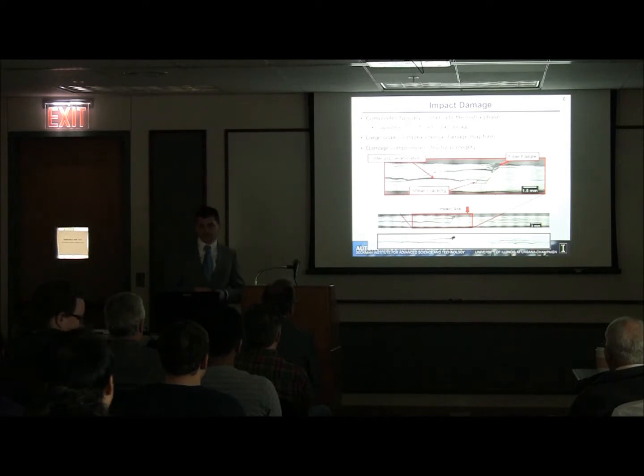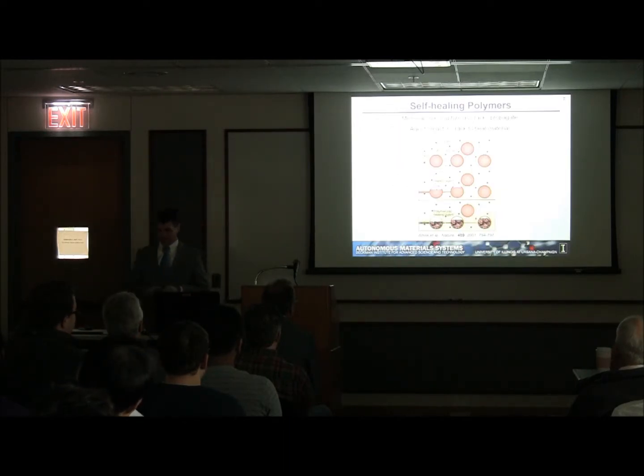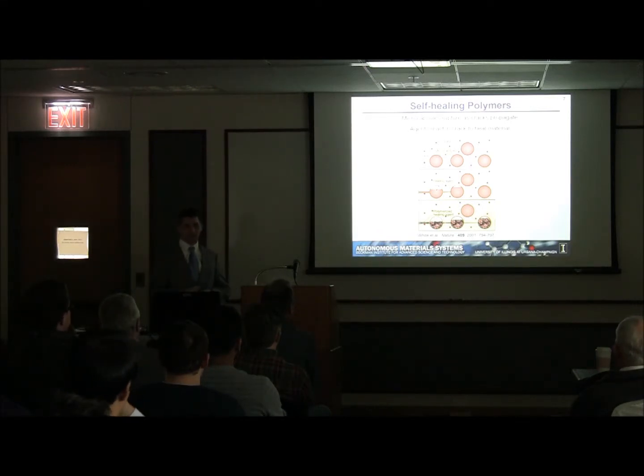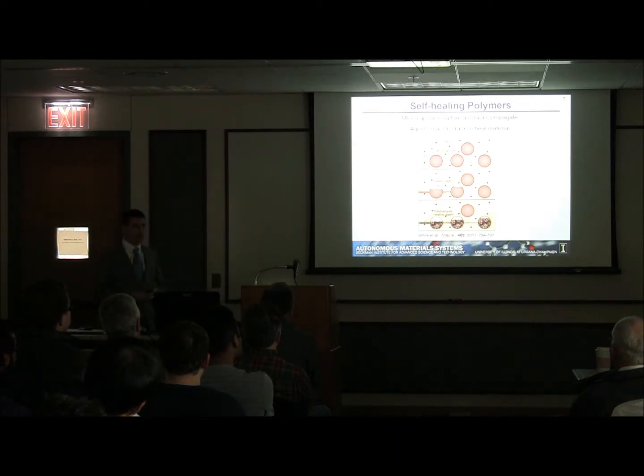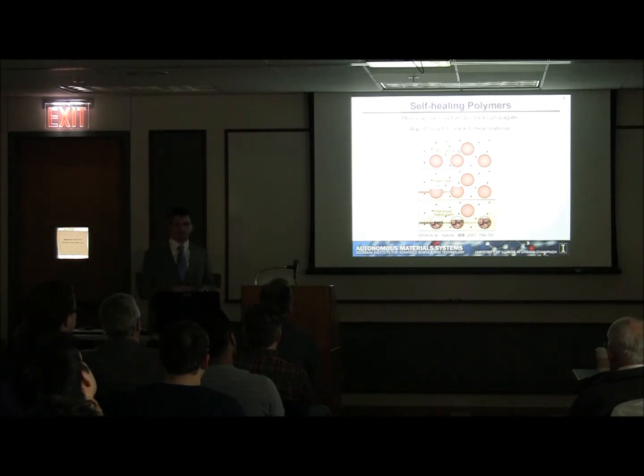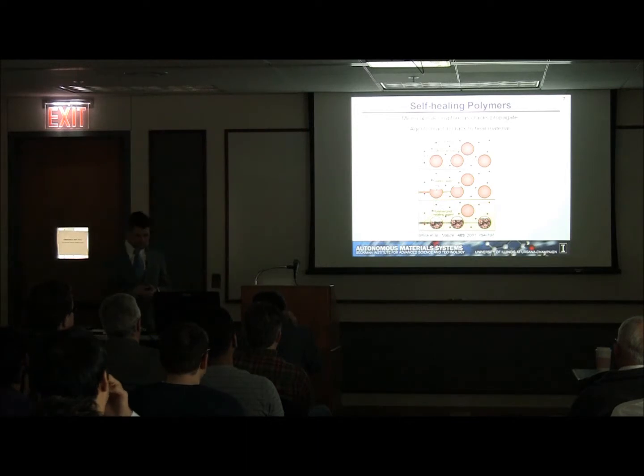And so here we're just showing a cross-section of a composite with a couple of different damage types. Here we see delamination between fabric layers, shear cracks occurring, and in some severe cases of impact we have fiber failure. Fortunately, I was lucky enough to join a group that worked with self-healing polymers, and the original idea behind self-healing polymers was we wanted a material that had the ability to heal itself when damage was introduced, automatically without human intervention. And that first demonstration was done in 2001 with a capsule-based system.